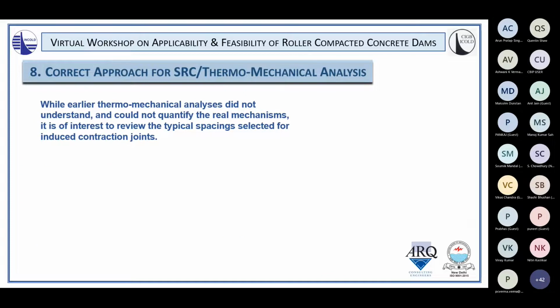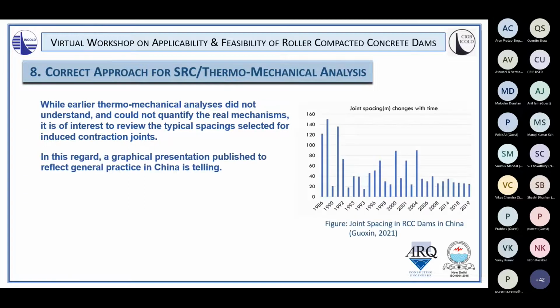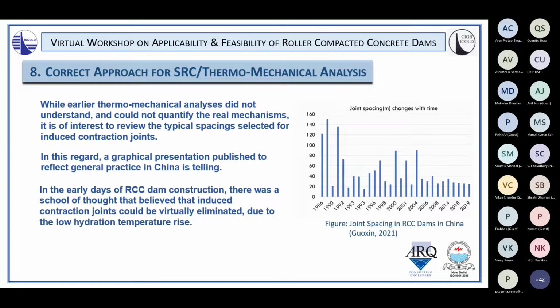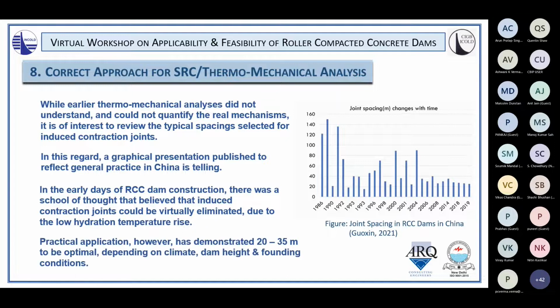So while earlier thermomechanical analysis didn't understand and could not quantify the real mechanisms that were occurring, the real stress relaxation creep mechanism, it's of interest to review the typical spacings selected for induced contraction joints over history with conventional dams. And in this regard, a graphical presentation published recently of Chinese experience is very telling. So in the early days of RCC dam construction, there was a school of thought that believed that induced contraction joints could virtually be eliminated in RCC dams due to the low hydration heat rise. But practical application has demonstrated that a joint spacing of between 20 and 35 meters is realistically optimal.